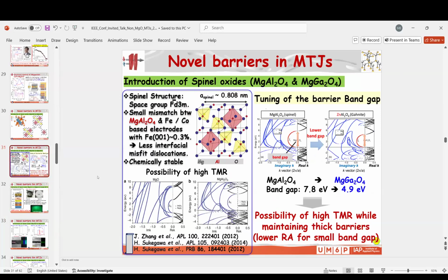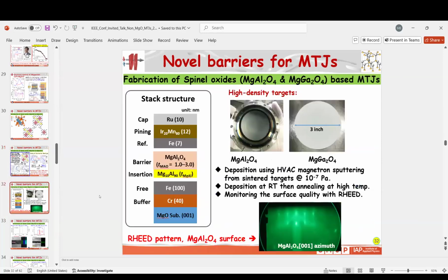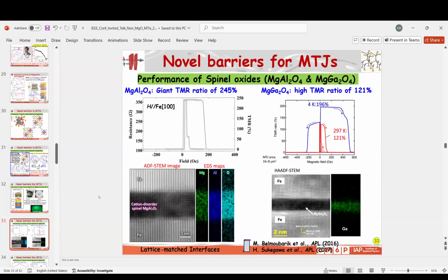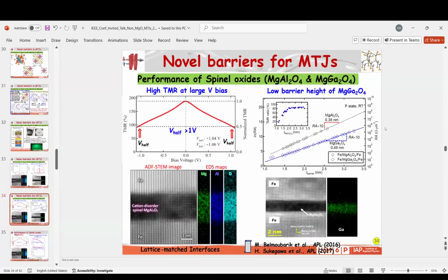But I think this can be solved by some doping. So we proved that we have high performance spinel oxide, and when we tackle the issue, for example, of low RA, this has been confirmed by using magnesium gallium oxide. Since it has a low band gap, using the same conditions we could realize a lower RA, which shows that we could realize low RA MTJs.